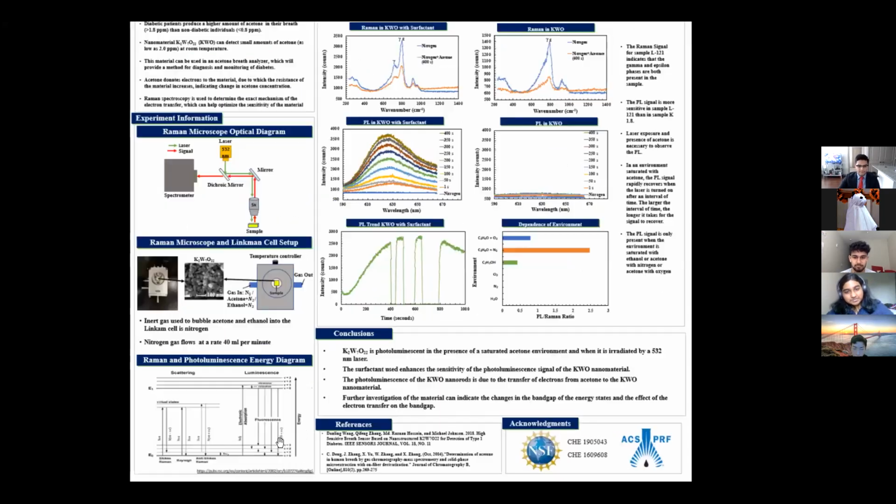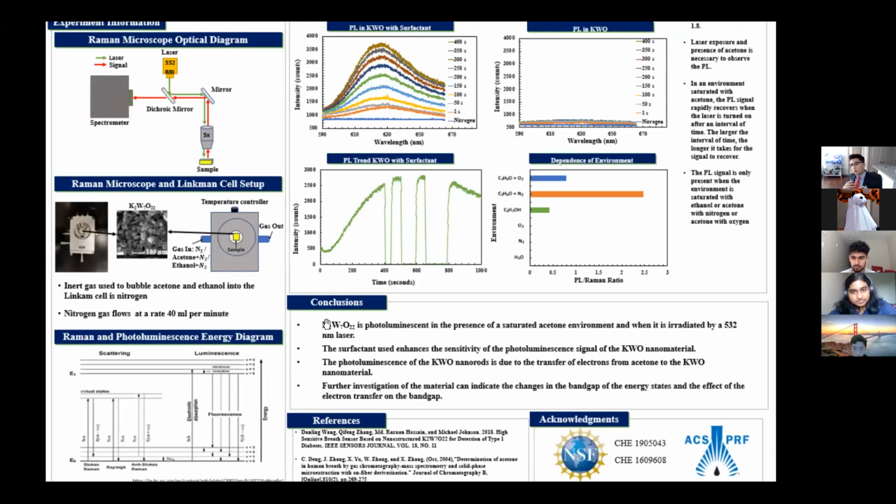All right. So what happens in defect states is when our material interacts with something, there can be the production of defect states, which essentially cause little variations in our band structure. So our conduction band up there can have little variations where it comes down to a lower energy state. What we're proposing is that the interaction with acetone causes a change of band structure that lowers our conduction band state.